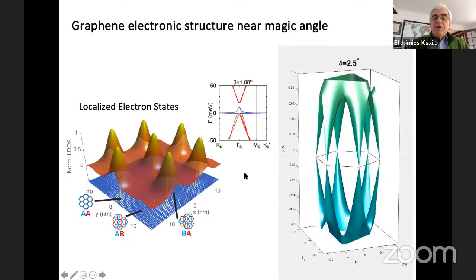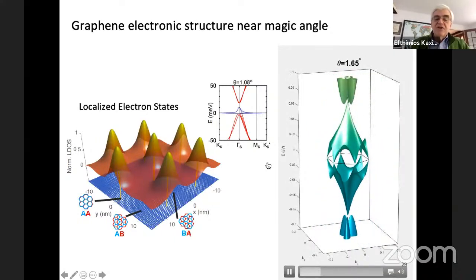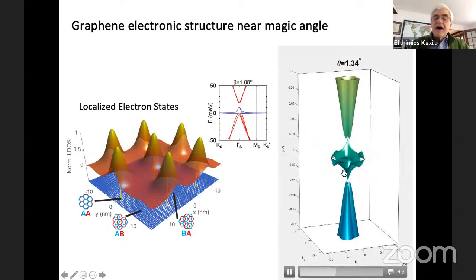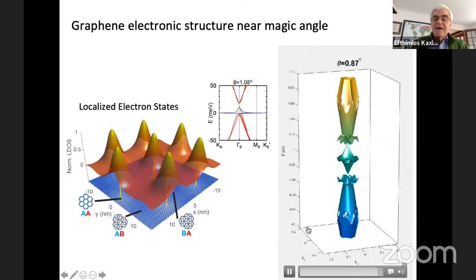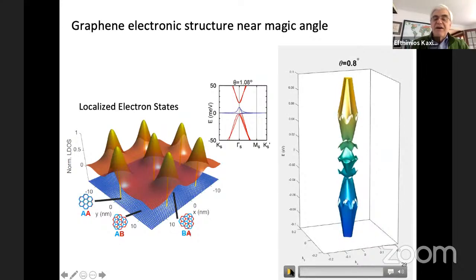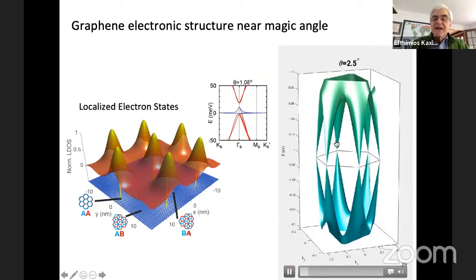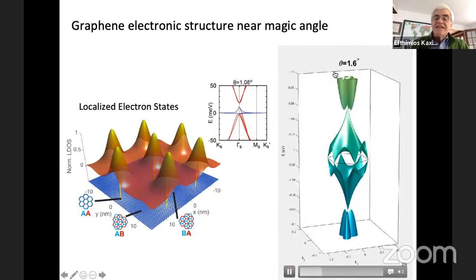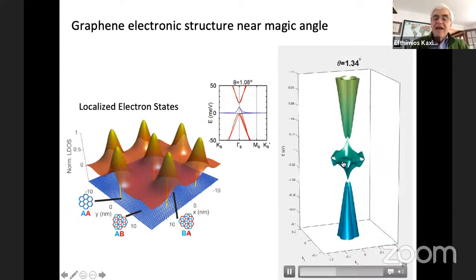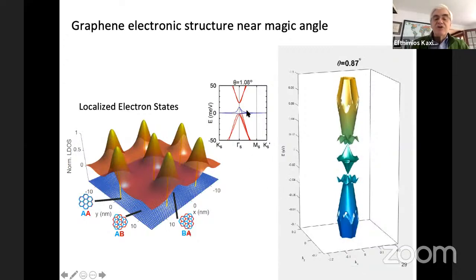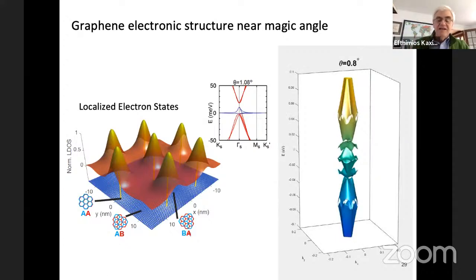The second thing is how the electronic states change as a function of twist angle. Here I'm showing you the Dirac cones as they evolve as a function of twist angle. And you see that at a magic angle of about 1.1 degrees, you get these very flat bands. I'll play this movie again. The movie starts with the Dirac cones that I was showing you earlier at a relatively large angle, about 3 degrees. The hexagon and the Dirac cones come together as the angle becomes smaller and smaller, at about 1 degree. The bands, instead of Dirac cones, become very flat. Those are the flat bands corresponding to the magic angle. And flat bands, just like those shown here, correspond to high density of states. That's where the high density of states comes from.